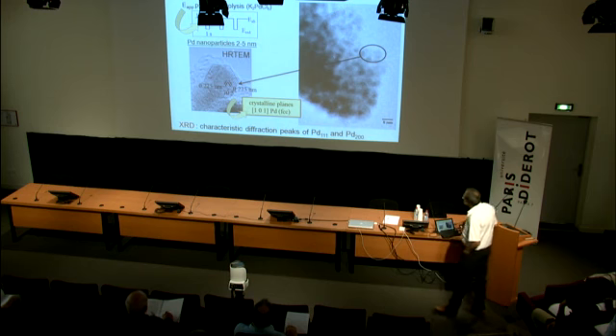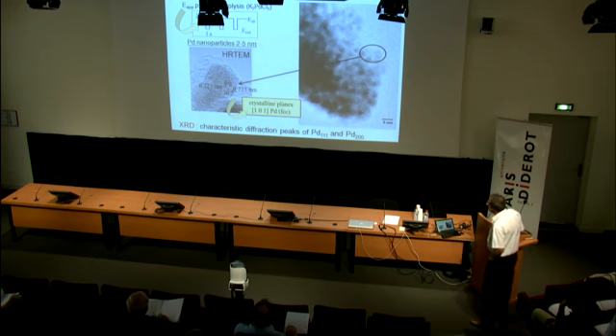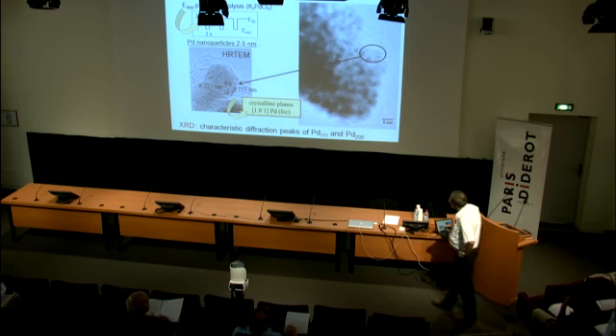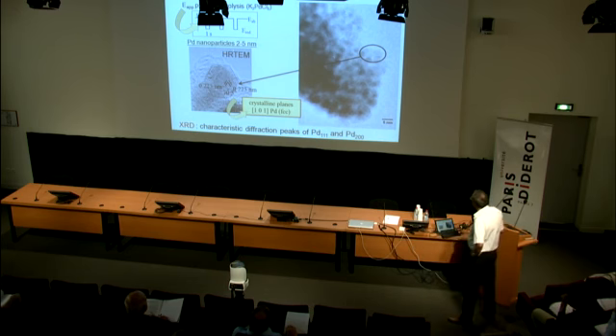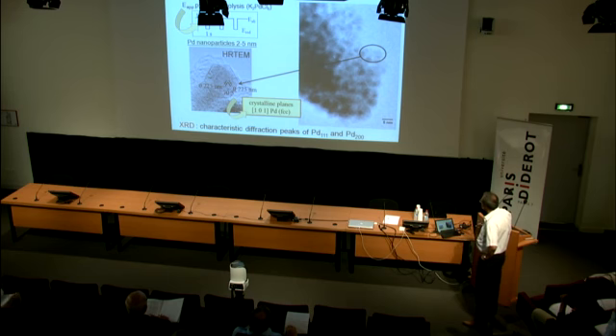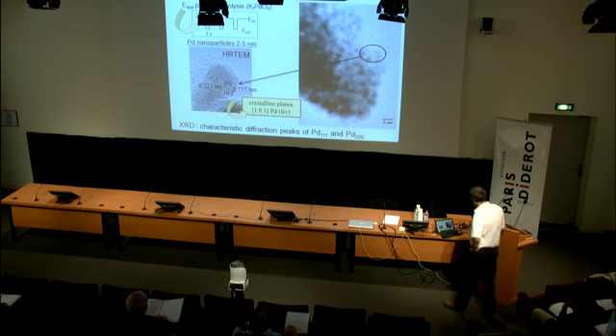And for instance, with the palladium, we obtain nice nano-dispersed particles in the polymeric film. As I said, with the palladium, that's the TEM picture here. And if you use a high-resolution TEM, you can observe the crystalline plane of the palladium.